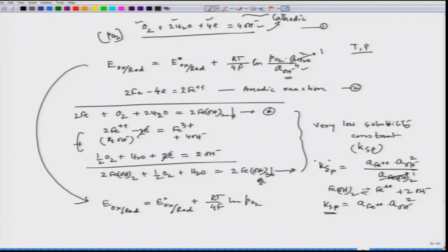Now once we have this relation, we see that if we have a difference in this quantity at two places, for example place 1 and place 2, and we have PO2 1 and PO2 2, then if this is greater than this, automatically we have E ox red 1 greater than E ox red 2. So that means that because of the difference in dissolved oxygen pressure in two places which are electrically connected, there is a difference in potential.